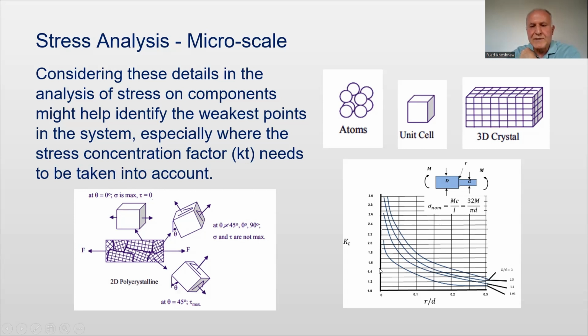1.5. What does that mean? That means the stress at this point is 1.5 times larger than everywhere else. Larger than here, and of course here, because this is a higher diameter, there is lower stress. But it is even 1.5 times larger than the smaller diameter. So that's something correlating with the structure of the component from outside, how it looks. If there is a discontinuity in any way, then KT must be considered in the calculation. And from inside, the microstructure, these atomic plane orientations need to be considered to find out the highest stress that can be there based on this orientation.